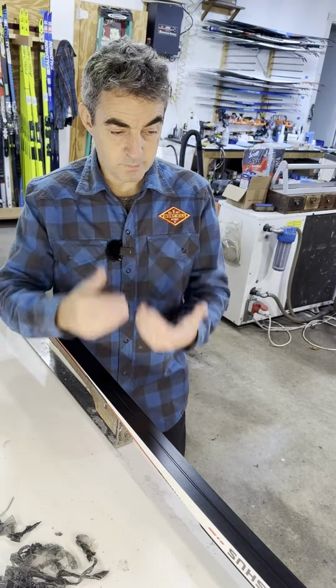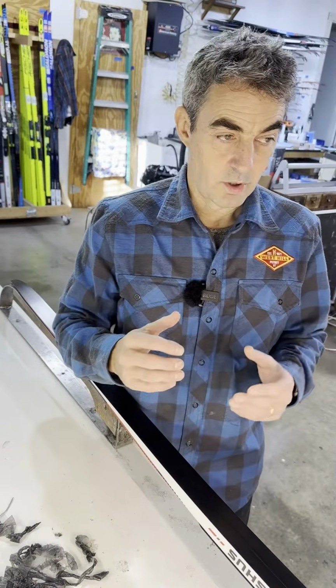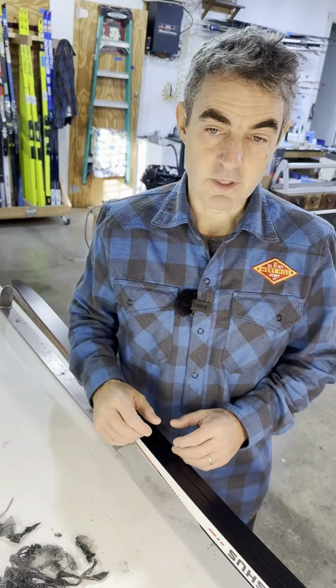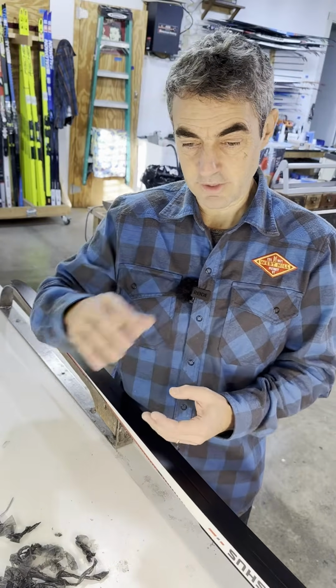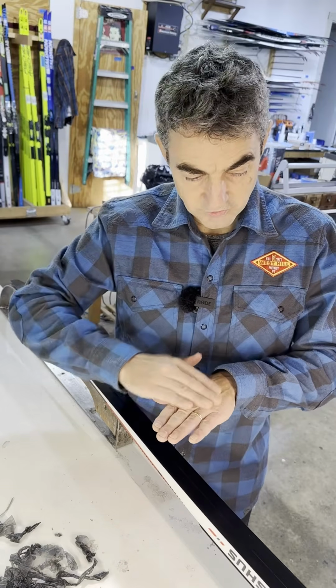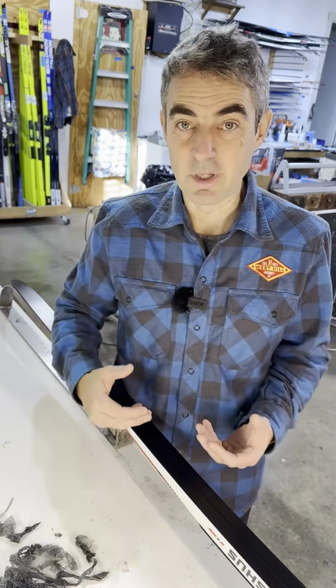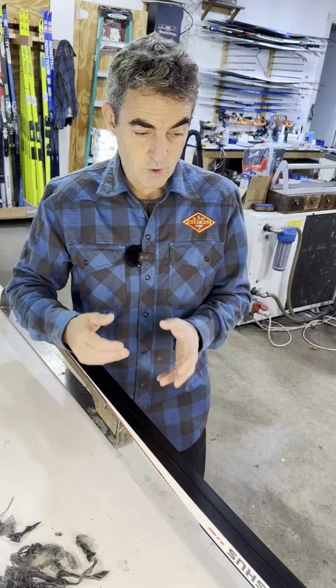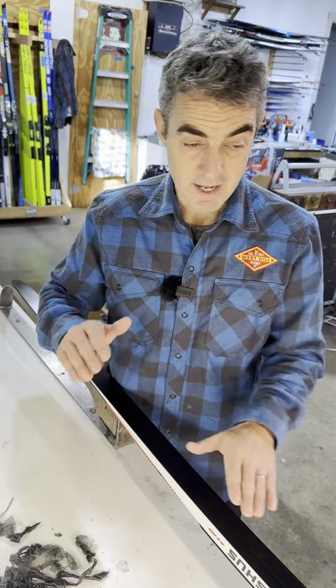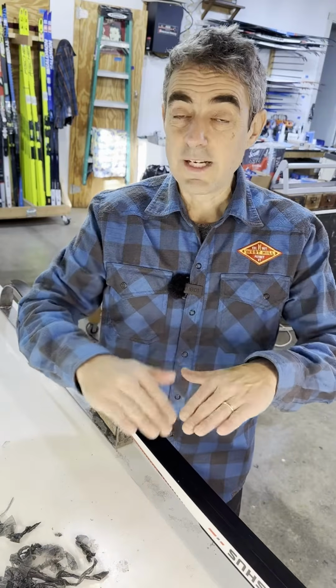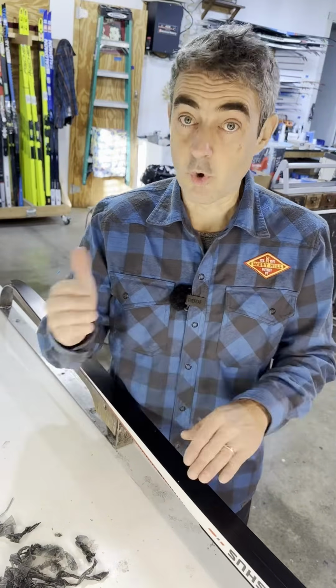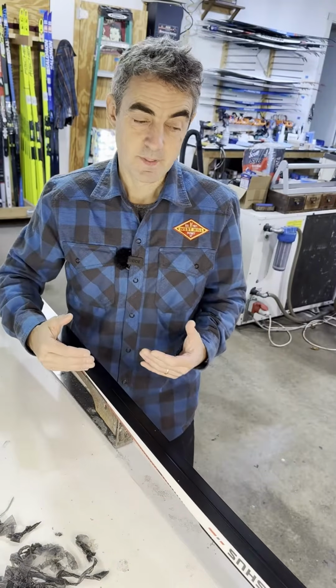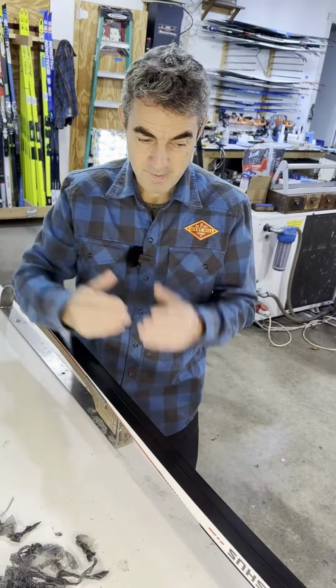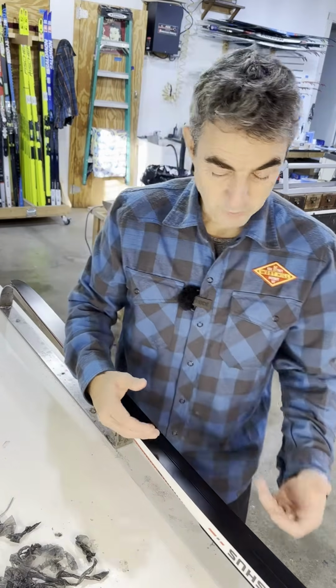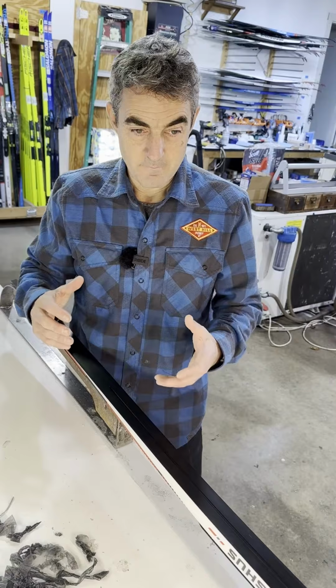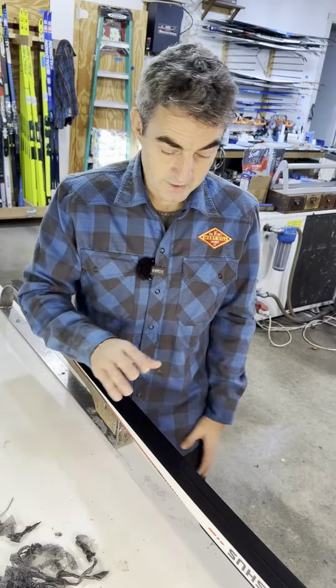Normally, when we are purposefully building our surface layers, we're addressing the bigger part of the equation. Most of the performance you get is the lubricity that comes at that surface layer. The wax is just sitting on the surface of the ski, and all these cold applied solutions give us a way to not only apply a surface layer, but apply discrete surface layers that can mix together or be held separately. It's like kick waxing. But kick waxing without the base wax doesn't often work. The binder, the base wax, gives you your suspension, the bulk properties that you need to really support the whole process. It's the same with glide.